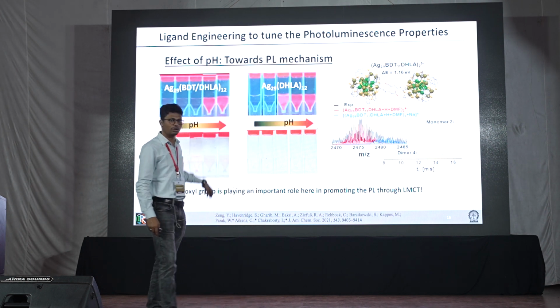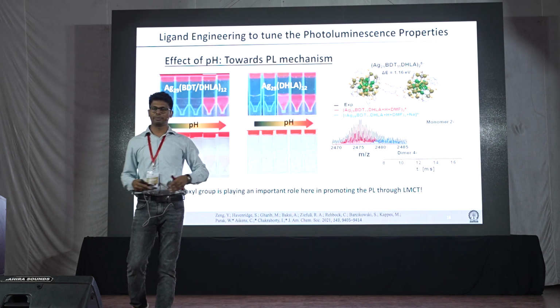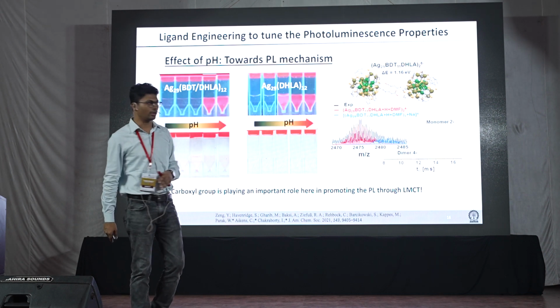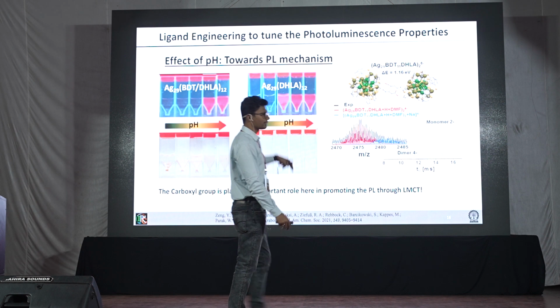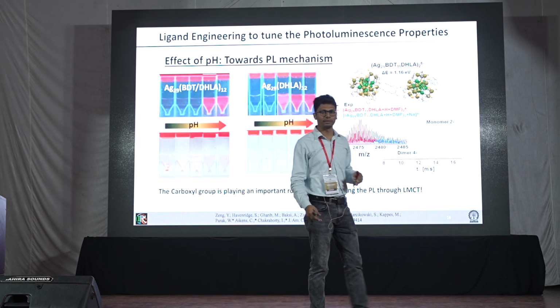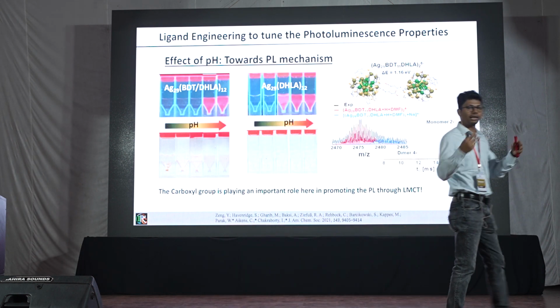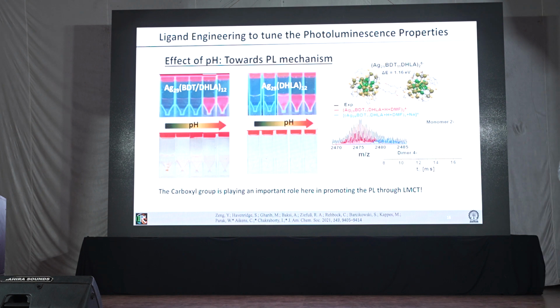So we aggregated based on pH values, and we see nothing happens there. So it's not an aggregation-induced emission. Now what exactly is happening is what we saw in mass spec, that there is a dimer. Professor Pradeep has mentioned that dimerization occurs between clusters, right?